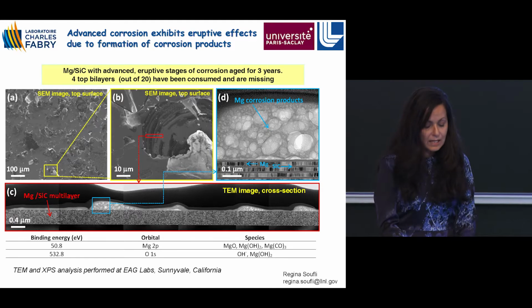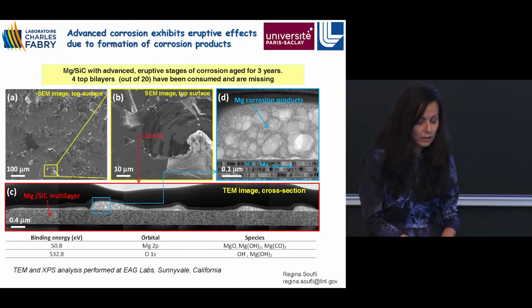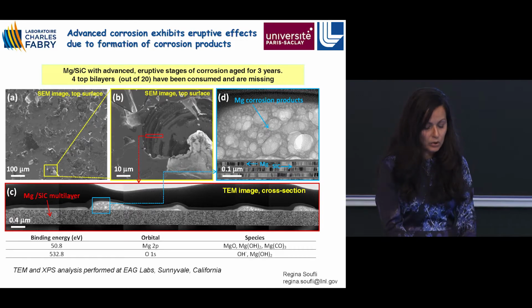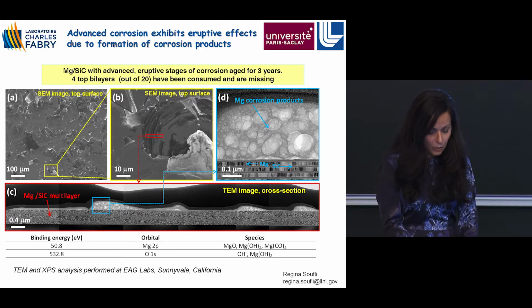We decided to investigate this effect in detail. Again, we started from one of those SEM images, and we cut a cross-section. Let me go into the zoom mode again. So we went into one of those craters, cut a cross-section, and did cross-sectional TEM. Here is the multilayer. You can see it. And then on top of it, you can see the corrosion products.